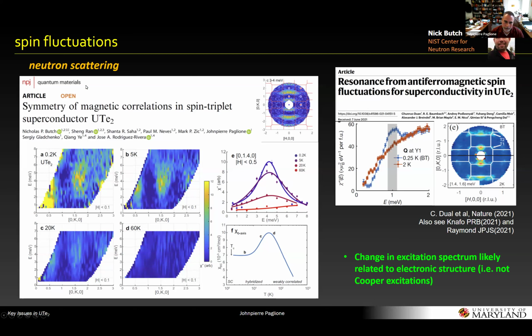Now, on the flip side, my colleague Nick has a different interpretation of this. In particular, he notes that you can see the evolution of the spectrum from high temperature. In fact, it evolves from where the Kondo lattice state turns on all the way down, and it sort of goes right through TC. And he claims it's more consistent with possibly interband transitions to do with the Kondo state that forms. And so this, of course, needs more work, and I know that there's some work going on to understand this picture. But if this is true, then you don't just necessarily assign a Q vector to the intensity. You have to understand what the intensity is about. Okay.